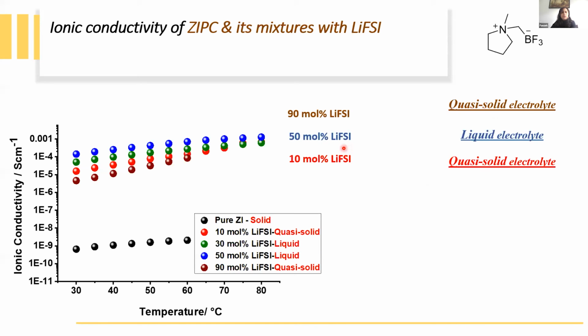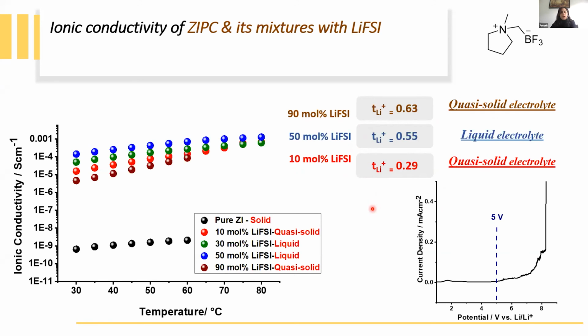And the interesting thing is that at low concentration and high concentration of lithium FSI, we have quasi-solid state electrolytes, and at the middle concentration, we have liquid electrolyte. Lithium transference measurements showed that the lithium transference value is relatively high, and especially at higher concentrations of lithium salt, we have a very high lithium transference number. We also measured the electrochemical stability of these materials, and the results showed that the materials are stable up to 5 volts. That means that we can use these materials with high voltage cathode materials to have higher energy density and higher capacity batteries.